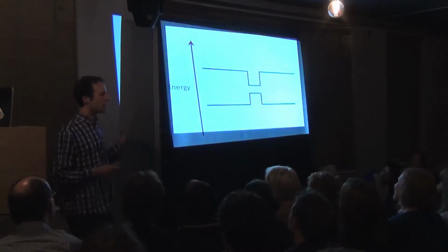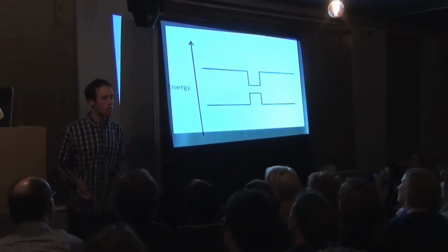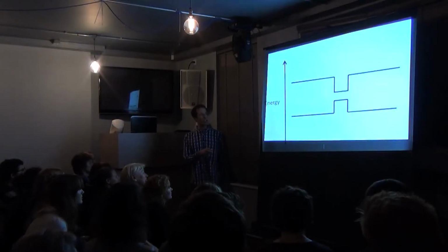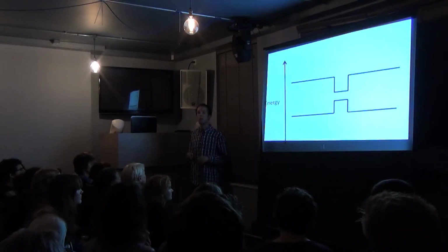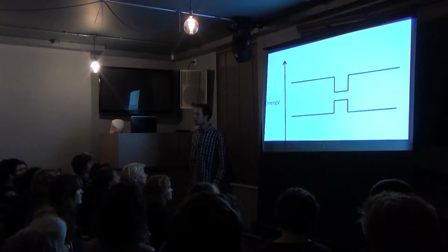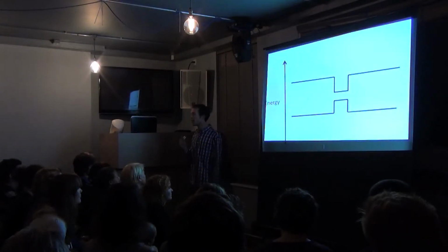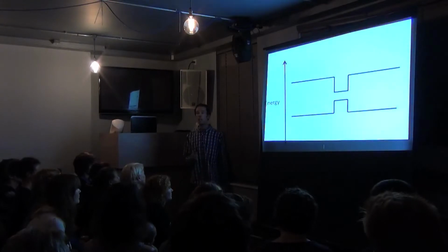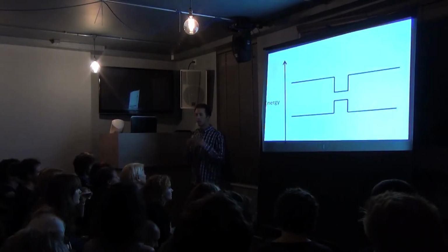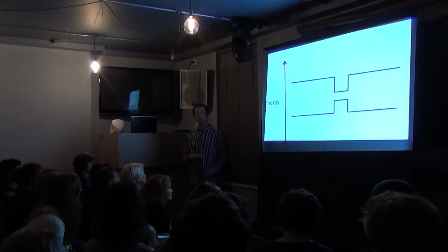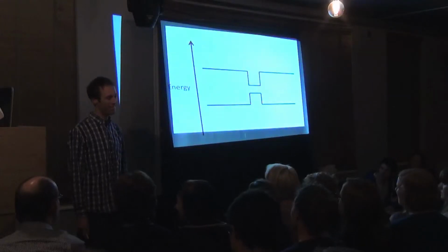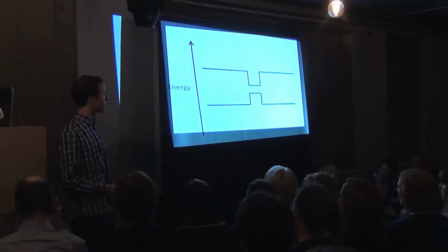First thing is I do all the calculations and design something. Then I get this grown for me. So there's a machine called a molecular beam epitaxy machine, which very, very slowly deposits atoms on top of each other. To grow this bit in the centre, we have to deposit it at less than one layer of atoms a second. Luckily, if we do that, this bit, the island of this lump of indium arsenide, it just clumps together naturally, which is great. What's not great is the machine that we needed to do this slowly broke, and I couldn't do any experiments for a year. So that's one of the downsides of being an experimental physicist.